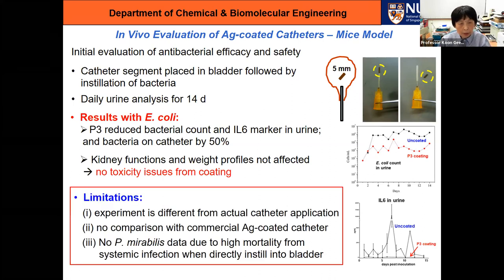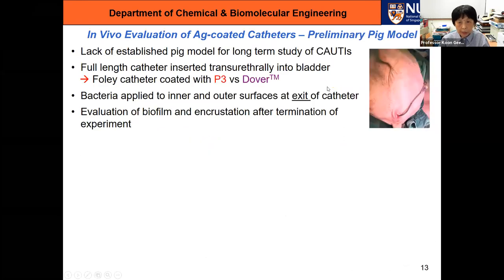But we know that this experiment has certain limitations because the way the catheter is being introduced is very different from how a urinary catheter is being used. And also, we cannot compare with any commercial silver-coated catheter because they don't make them so small. And we did try with P. mirabilis, but it's a bad idea because the mortality rate is very high when we introduce this bacteria into the bladder itself. So we decided that we will go on to the pig model, where we can use the full-length catheter like in the human.